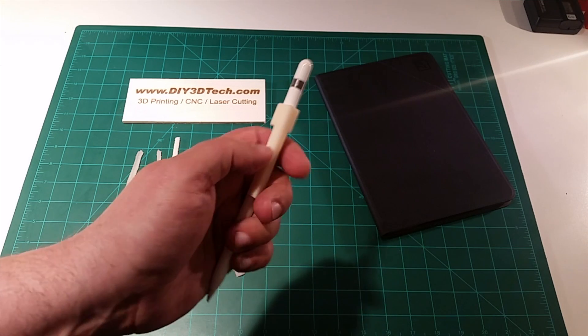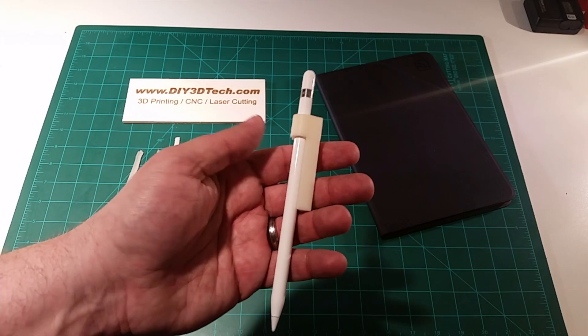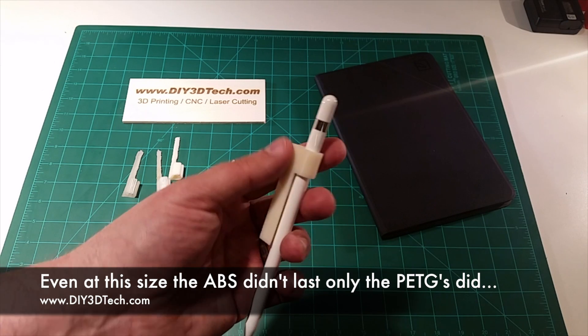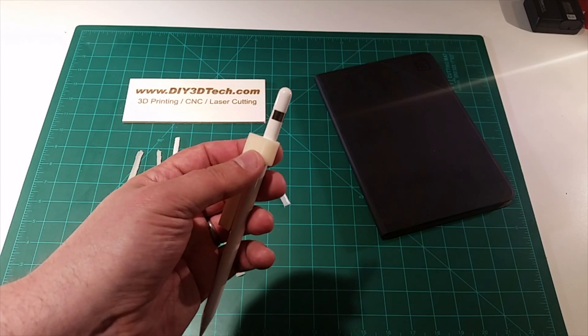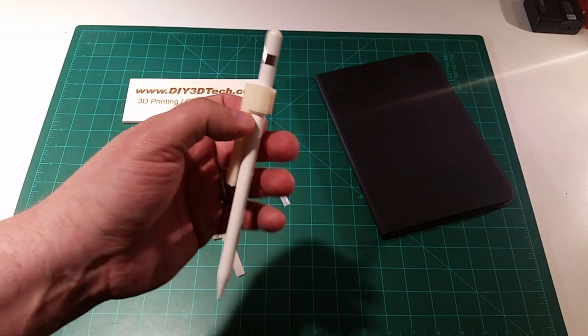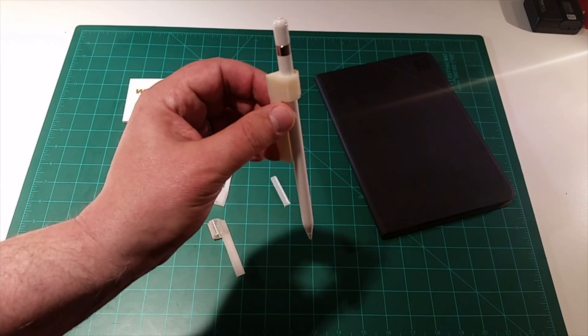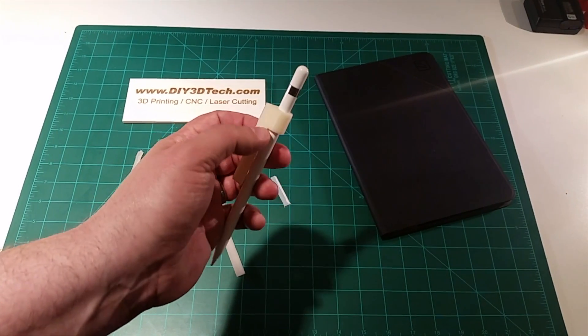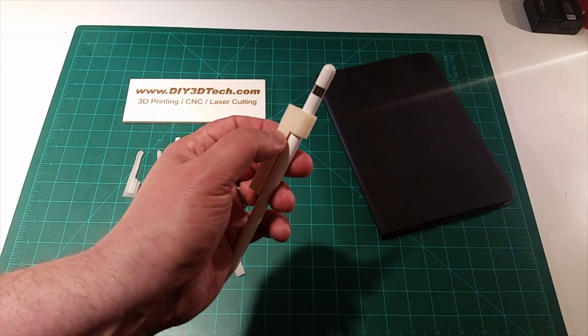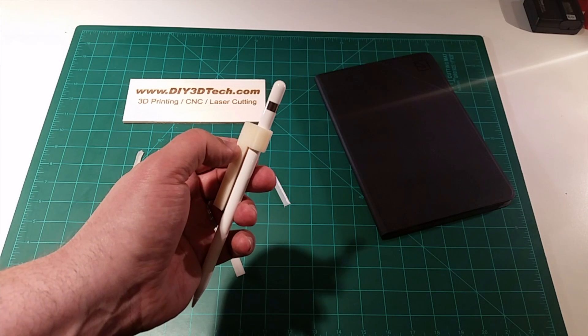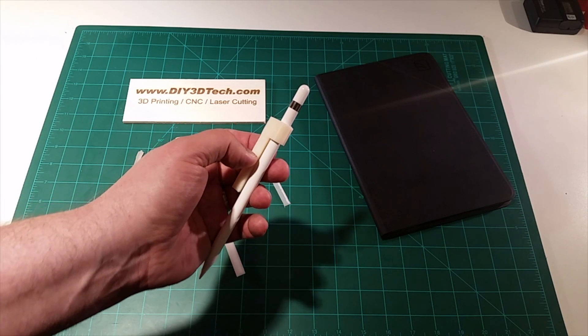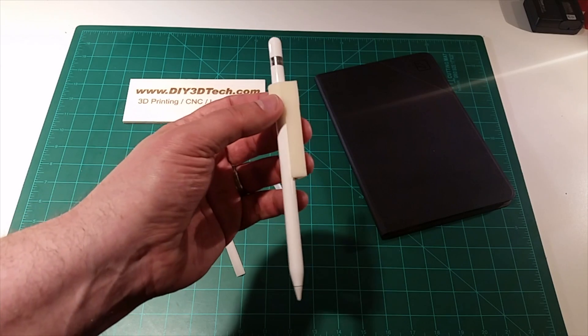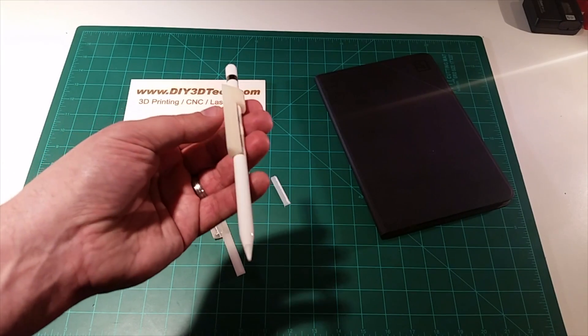It is very light here. One of the things, I'm not a fan of acetone smoothing, but if you did it in ABS and you are a fan of acetone smoothing that might be an option to bring some of the layers together. I might try printing this a little bit differently, actually printing it with supports, printing it this way up or on its side to change the direction of the filament. There's a band here and that's what's breaking because there's no real good join between the layers. If this was more of an injection molded piece obviously it would be like ten times as strong.